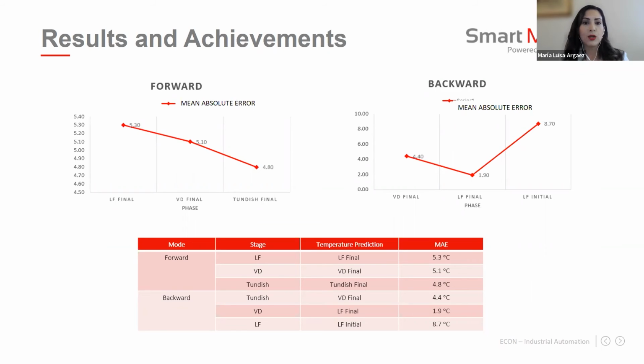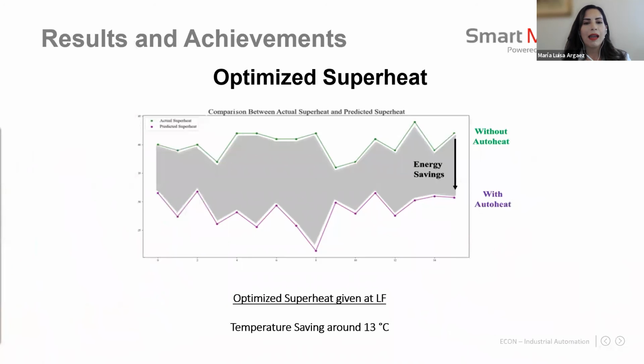And these temperatures were used to calculate the superheat needed for the heat to reach the proper temperature in the tonnage. So now let's see about the superheat. In this slide, we can see the estimated value in purple color and the actual superheat value in green color. It is seen that the estimation is lower than the real one, since the difference between the actual and the prediction is around 13 Celsius degrees. The temperatures were optimized to save energy and increase productivity, avoiding giving an unnecessarily high superheat.